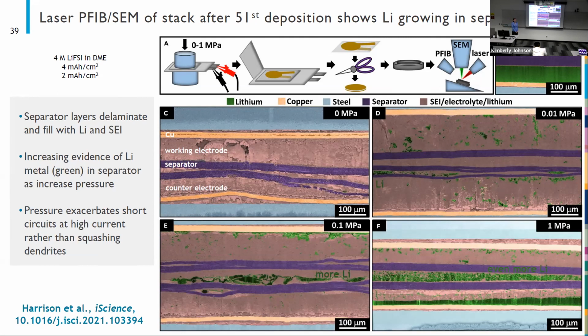We have done a lot of work trying to control pressure in coin cells too, and we've done a lot of work trying to change the springs out or stack springs and get to higher deflections to control pressure. But the problem with coin cells is that the seals aren't strong enough to withstand high pressure. If you can get springs that will go to high pressure and you just compress them more, you'll see that the cell starts to expand and the seals don't seal anymore. So coin cell crimp seals just aren't strong enough to withstand more than about 300 kilopascals of pressure.